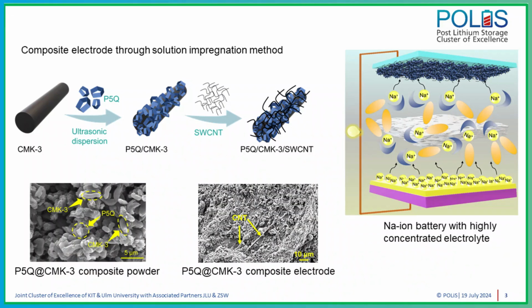Small molecule organic compounds have opened a new avenue for the next generation of green and sustainable battery. But their high dissolution into the electrolyte and poor electrical conductivity impede their further research progress. So in order to address this issue, we have adopted a dual mitigating strategy. Firstly, we have encapsulated the pillar-5-quinone into the mesoporous carbon to enhance its electrical conductivity. And further, we have made use of highly concentrated sodium electrolyte to inhibit the dissolution of the active material into the electrolyte and thus increase the electrochemical performance of the sodium ion battery.